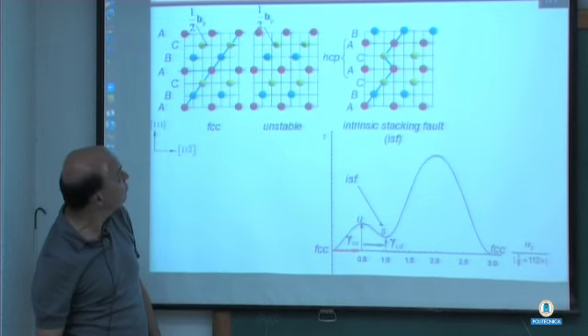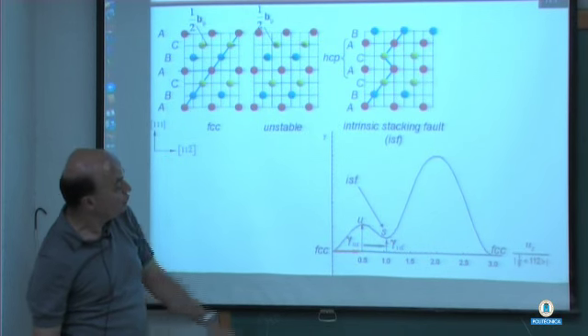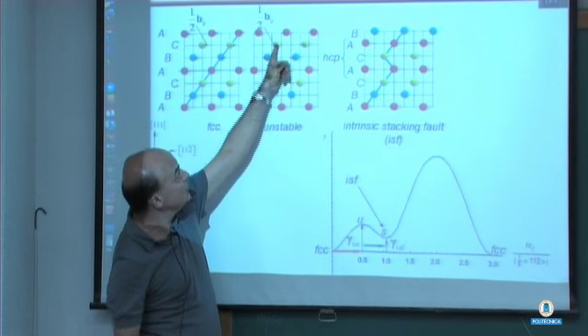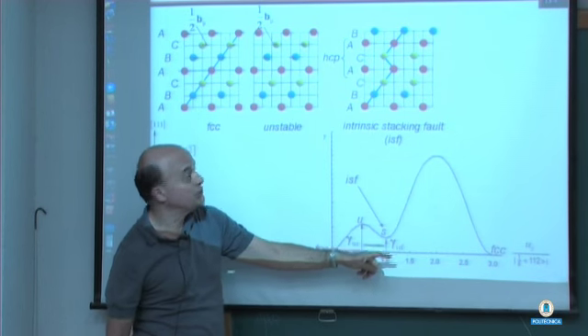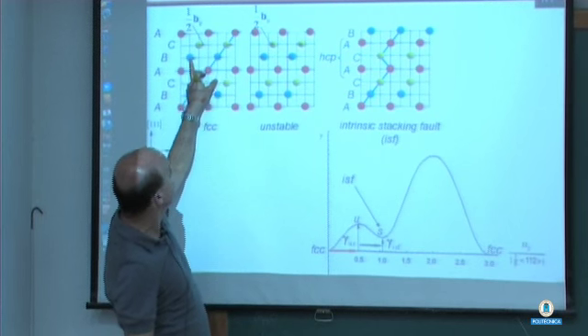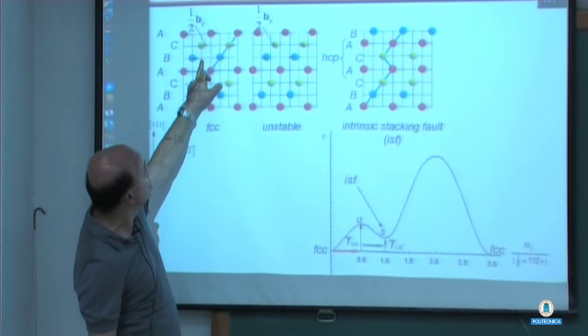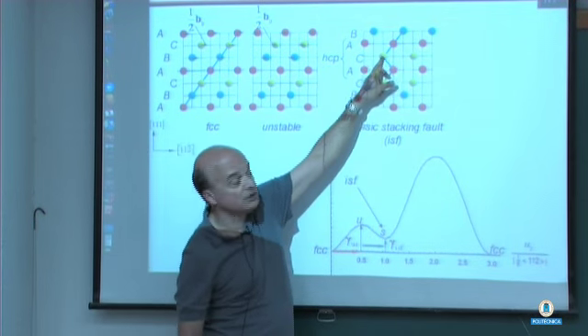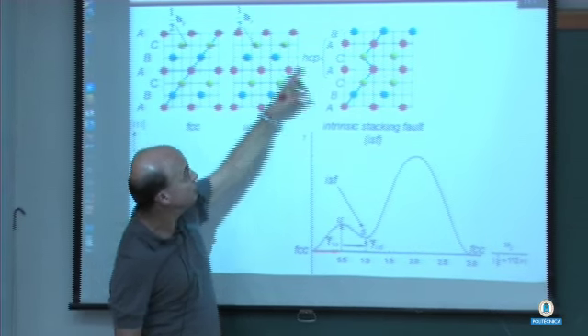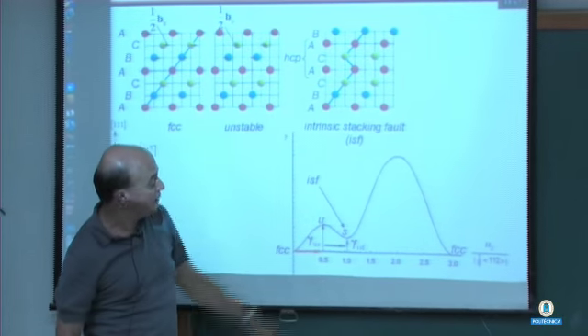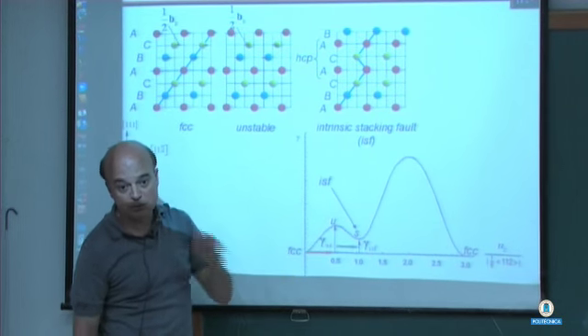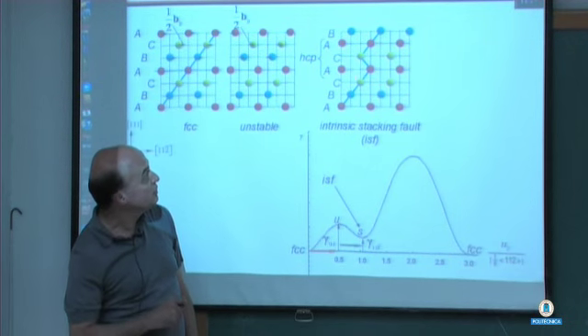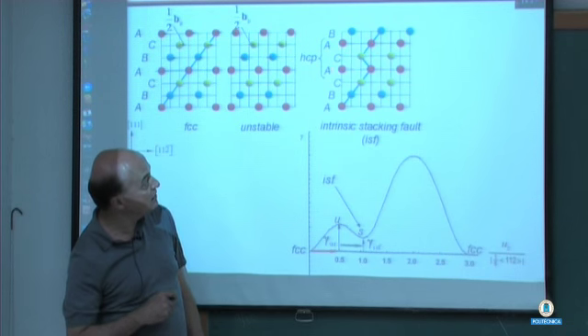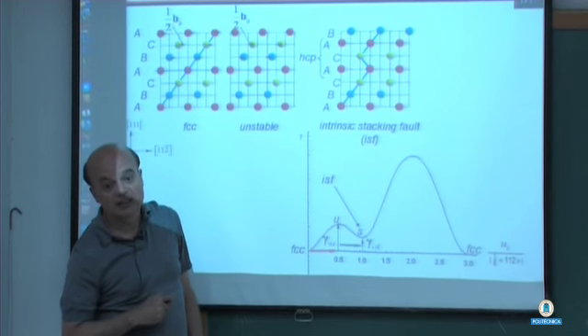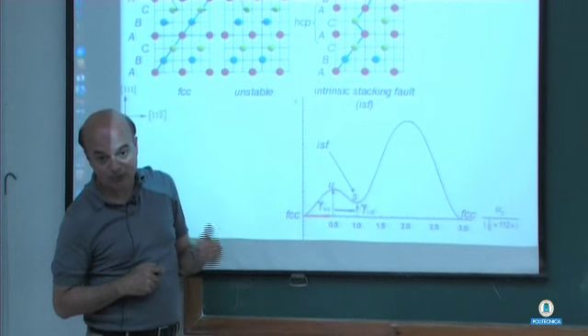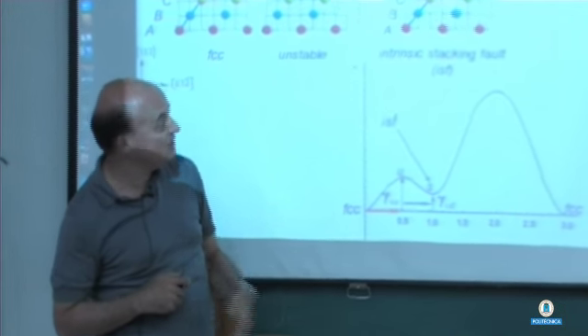Now if you move further, if you move these atoms another half a Burgers vector, then you have moved the blue atom into the green position, which is here, and then you have moved the green atom to the red position here, and that is a metastable position. That motion of the atom creates an AC stacking, and that is the stacking fault. Okay, that's what we mean by stacking fault.